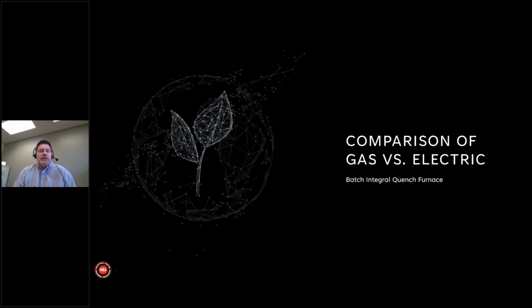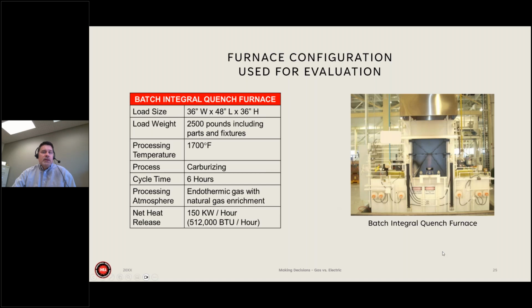So now moving into an example comparing gas versus electric. The first example is going to be a batch integral quench furnace. This batch integral quench furnace is shown in a photo on the right. It has a hot zone with the RX endothermic gas and natural gas enriching in the hot zone.